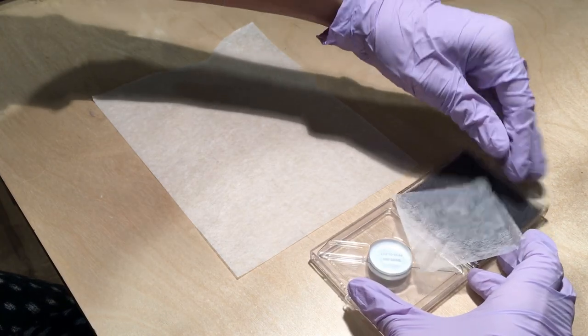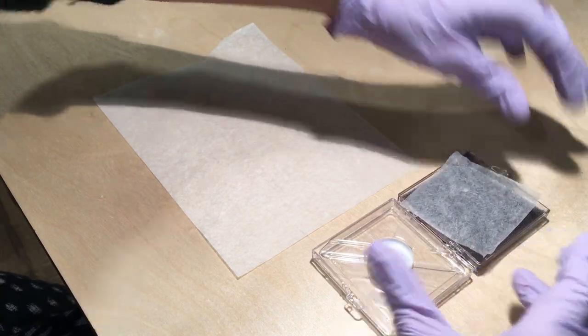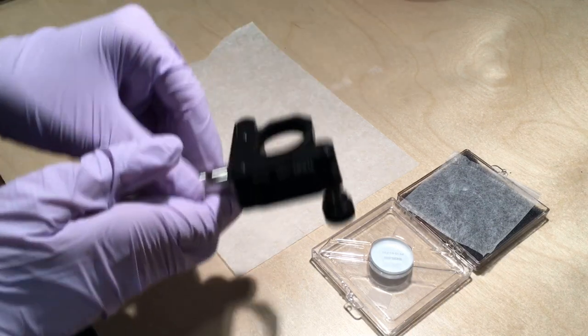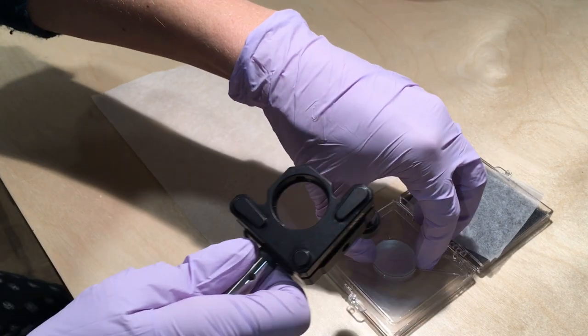Short of 400 nm, the reflectivity of aluminum is better than silver. A protective metal fluoride that preserves this reflectivity is an ideal choice in the UV.